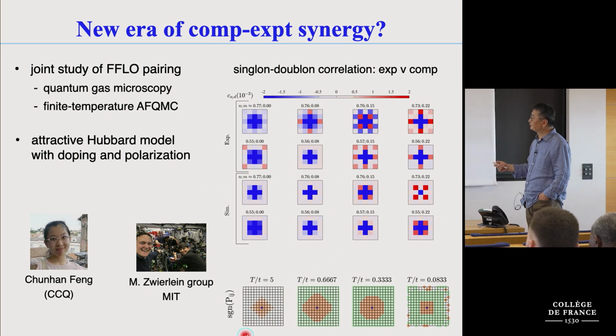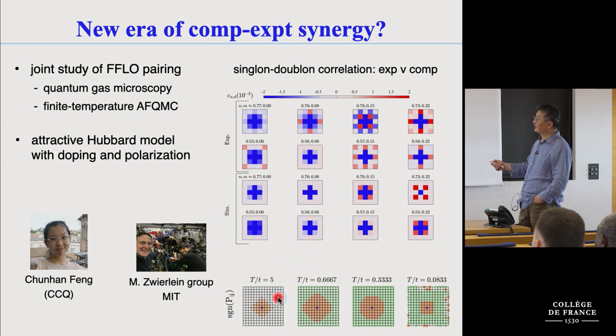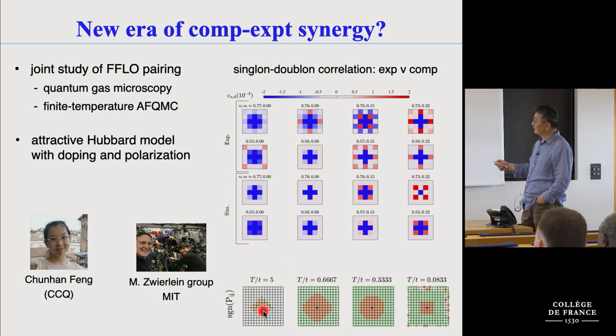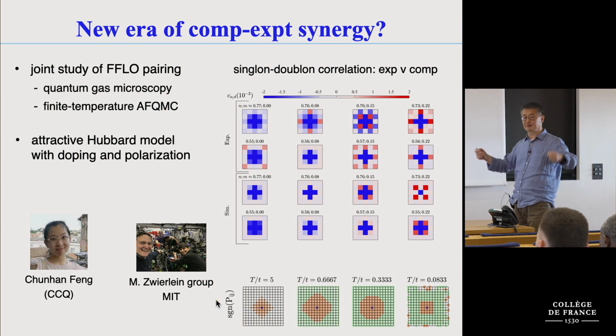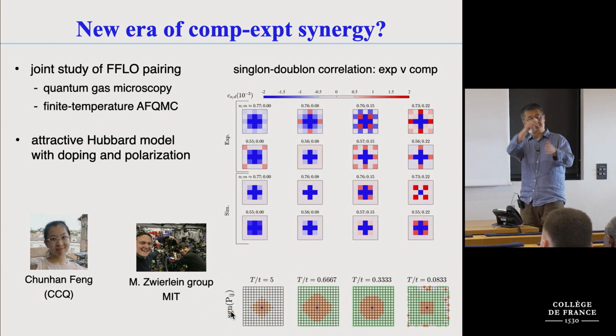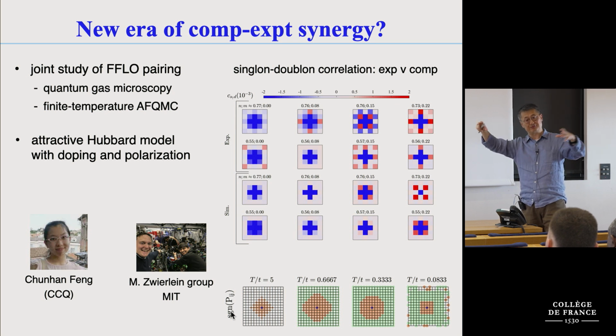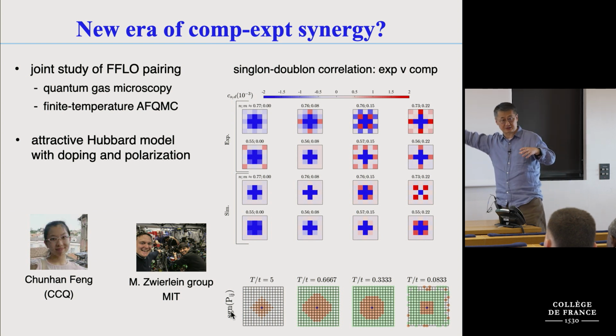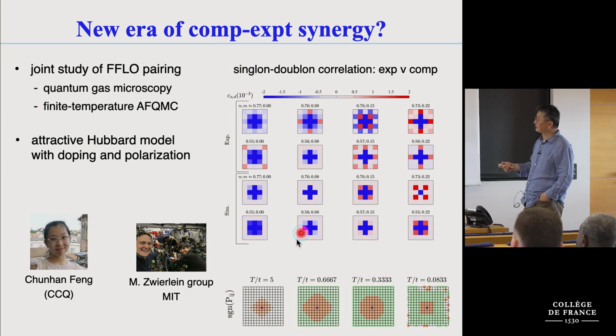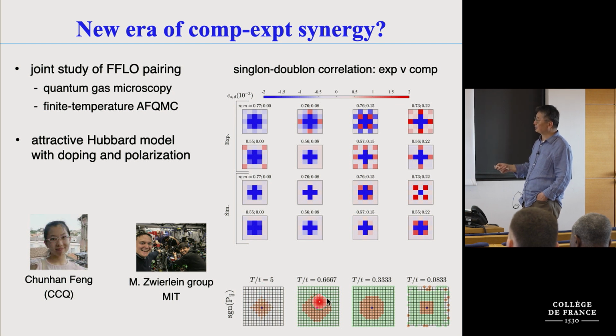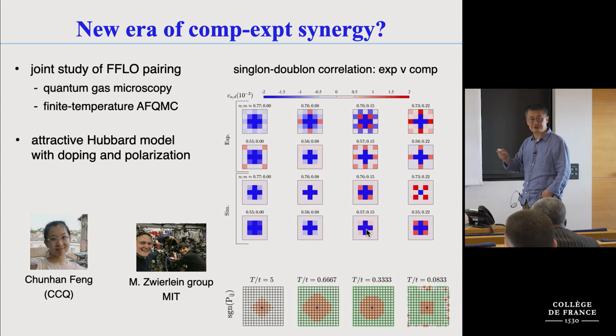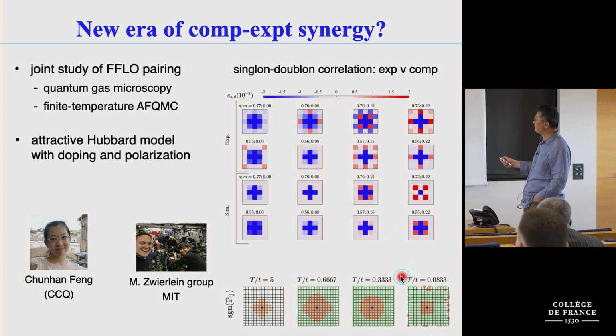And we look at the indicator for an FFLO order, this is the sign of the pairing correlation function. So the pairing correlation function should be a constant if it's long-range ordered. But if there's indication for FFLO, it would be positive, and then sometimes it's modulated, so it'll turn negative. So this is short-range correlation at high temperature, and then it changes shape, the order parameter, and then changes shape again. But eventually it starts to have one domain and then a negative domain and then a positive again. It starts to change sign. But at this temperature, of course, experiment is not quite here yet.